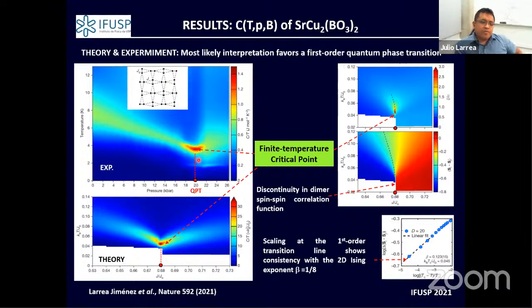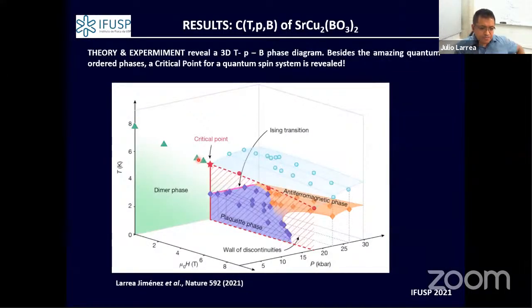Yes, it's a very interesting question. I think it's still an open question, in the sense that we are still exploring this phase diagram with magnetic field, right? Something we normally can attribute to this critical point is that at finite temperature, not only at zero temperature, you have this entanglement of states. But the point here is how this entanglement could become more and more dense, or even more robust, as you maybe wanted to know. Therefore, we still need to make more experiments to systematically tailor this kind of entanglement of the state according to how close we are to the phase transition, being continuous or discontinuous.